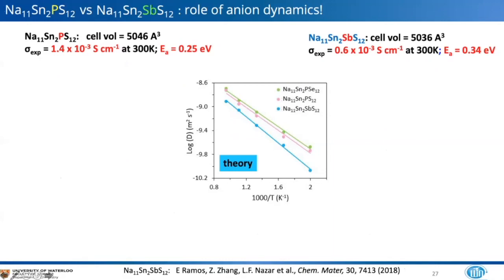So as we started to look for other analogs to this system, one of the materials we discovered was the antimony analog, which is shown here. It was reported in Chemistry of Materials about the same time. And we expected this to have better conductivity because of its larger cell volume. I have those numbers switched compared to the phosphorus. So this has the smaller cell volume, this has the larger cell volume, so you have to switch those numbers. So the point here is that the conductivity is about half that of the phosphorus analog, and the activation energy is much higher than that of the phosphorus analog.